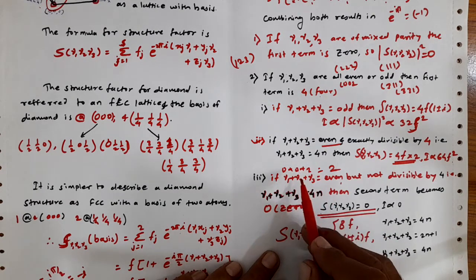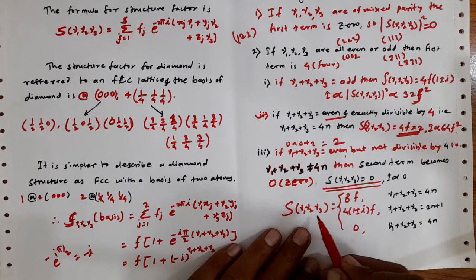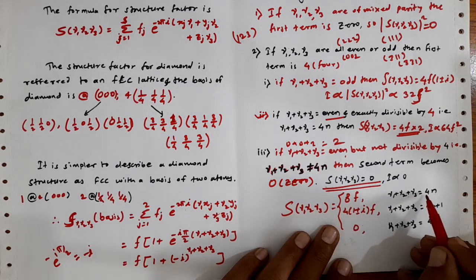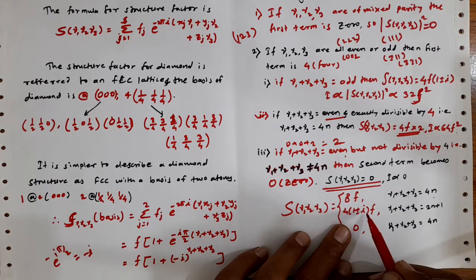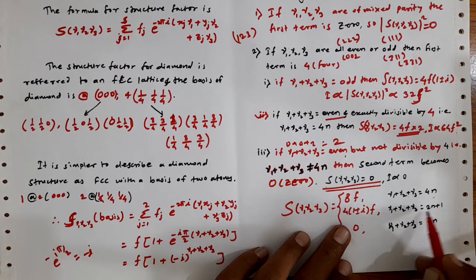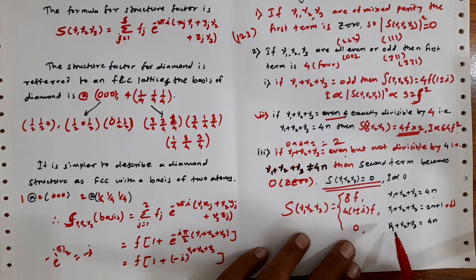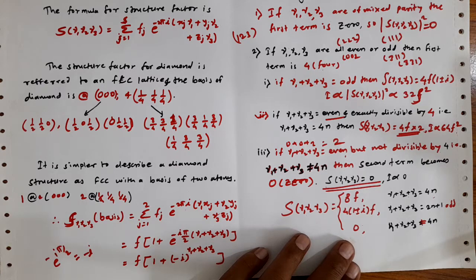To summarize: when ν₁ + ν₂ + ν₃ = 4n, the scattering amplitude is 8f with intensity 64f². When ν₁ + ν₂ + ν₃ = 2n+1 (all odd), the amplitude is 4f(1±i) with intensity 32f². When the indices are of mixed parity, the amplitude is zero — no reflection. When the sum is even but not equal to 4n, the amplitude is also zero — no reflection observed in the diffraction pattern. Thank you.